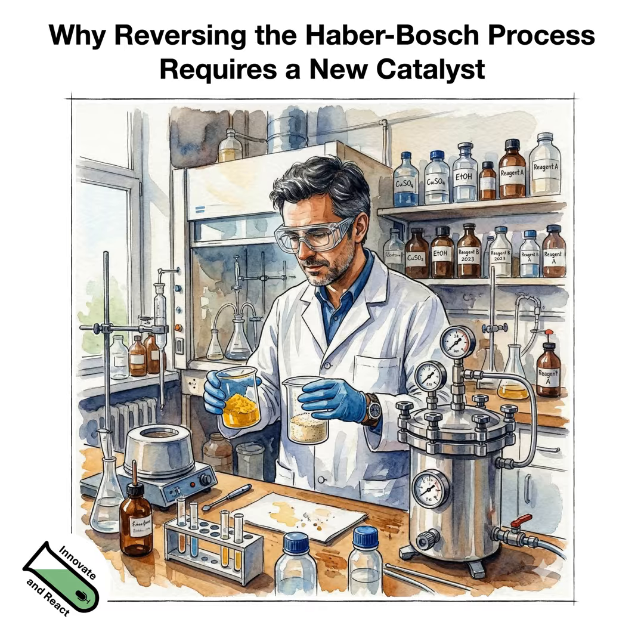The dispersion in catalysis typically is referred to as the fraction of surface atoms versus the overall amount of atoms. And there are other definitions in colloidal chemistry of the dispersion that are more on a particle basis. But here we can have one large particle of, let's say, a mixed hydroxide. So we have iron, cobalt, and magnesium in one hydroxide phase, and we have a large particle of that, and that is a solid solution.